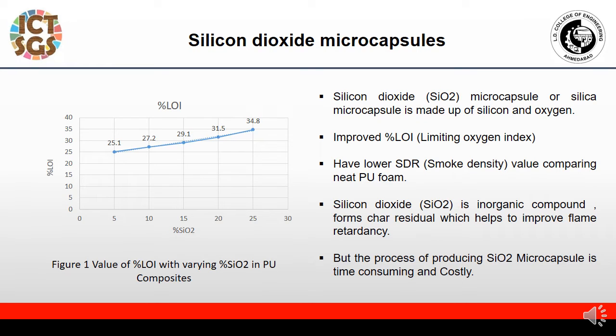Silicon dioxide microcapsule, or silica microcapsule, is made up of silicon and oxygen, which improves the percentage LOI, limiting oxygen index, as per figure 1. The value of the percentage LOI with varying percentage of silicon dioxide microcapsule in polyurethane foam is shown. It also shows a lower SDR smoke density value compared to the neat polyurethane foam. Silicon dioxide is an inorganic compound. It forms char residue, which helps to improve the flame retardancy property. But the process of producing the silicon dioxide microcapsule is time consuming and costly.